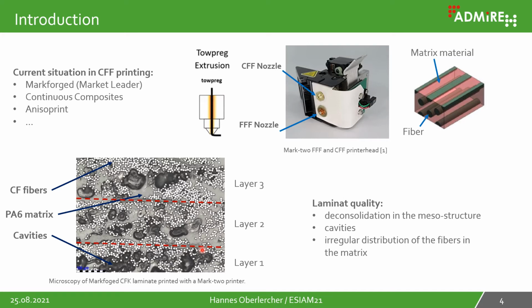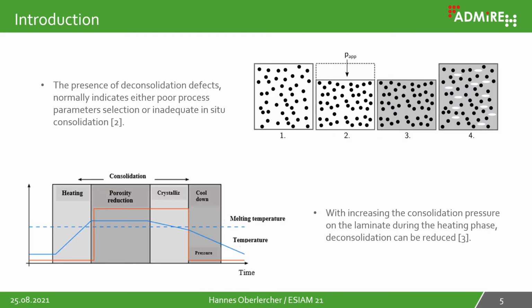We also analyzed the laminate of this printing technology. You see here in this microscope image 3 layers, and it shows some imperfections. It's a kind of deconsolidation in the mesostructure. There are some cavities, these black holes, and also an irregular distribution of the fibers in the matrix. These imperfections lead to a reduction of the mechanical properties, and therefore this kind of high performance material cannot use its full potential. How can this deconsolidation or relaxation appear after the printing process?